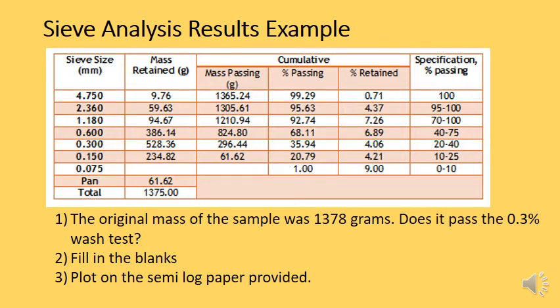So with the 2.36 millimeter sieve, the second column, we're trying to work out the entire mass which is smaller than that. So that'll be 1,375 minus 9.76 minus 59.63. The 59.63 and the 9.76 are the masses that were caught by sieves larger than 2.36. So 1,305.61 grams passes through.